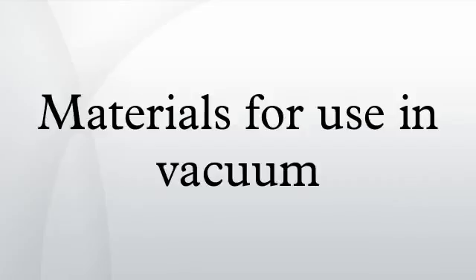Fiberglass composites, for example micarta and G-10, should be avoided. Even Kapton and Teflon are sometimes advised against. Various residues, for example flux from soldering and brazing, and lubricants from machining. Thorough cleaning of the parts is important. Getting the outgassable residues from tight crevices can be challenging. A good mechanical design that avoids such features can simplify one's life.